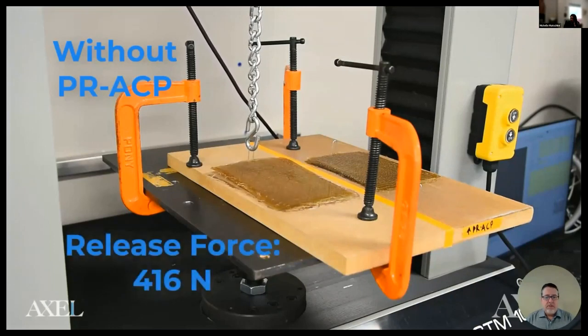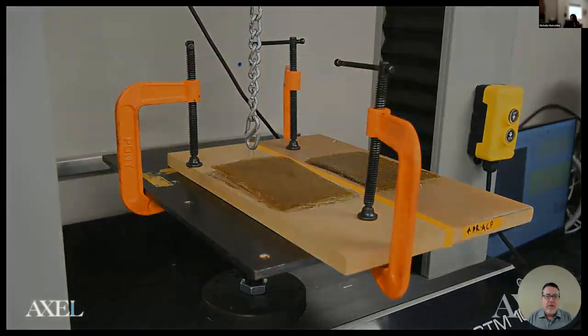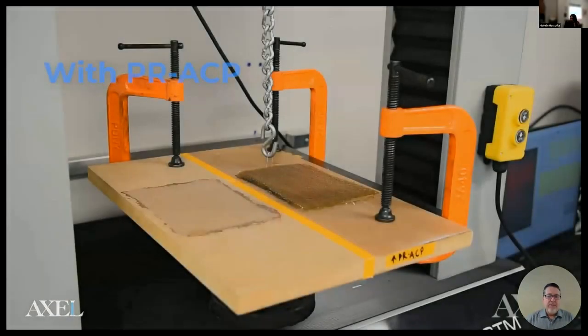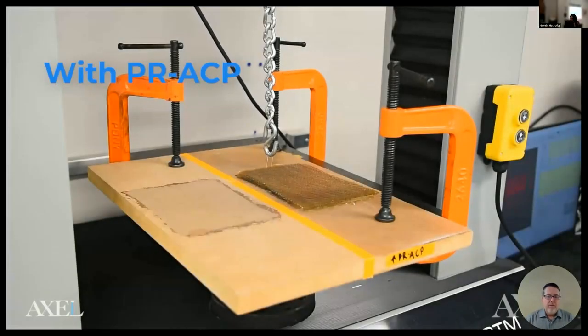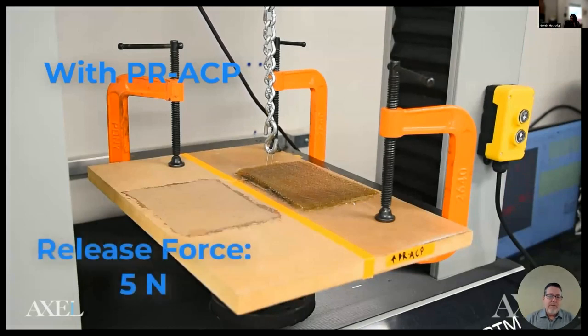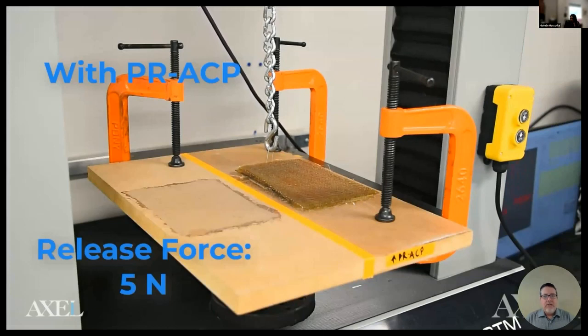You can hear the cracking and popping of the part being released without primer. So it makes the release system more effective and helps fill in the porosity. Also for fiber products, it helps block any natural oils or materials that are in there which can contaminate some release systems.